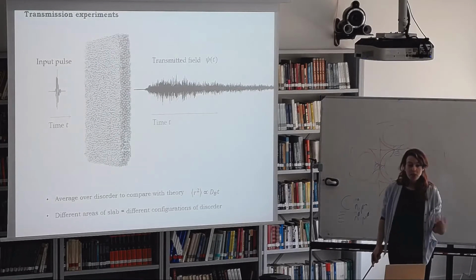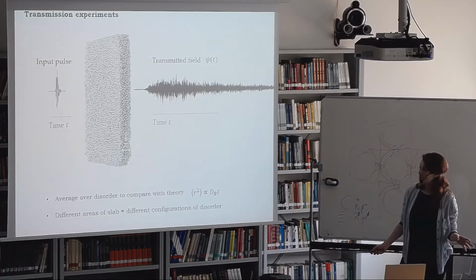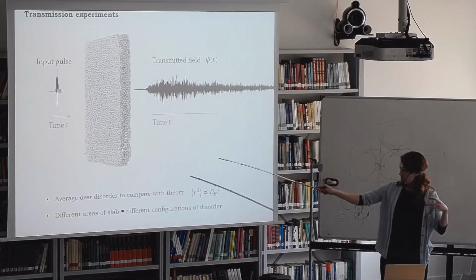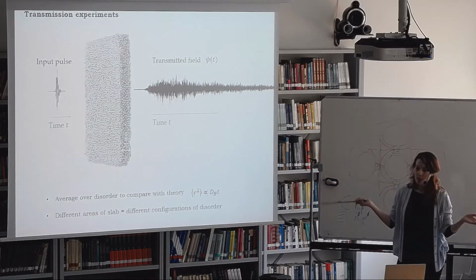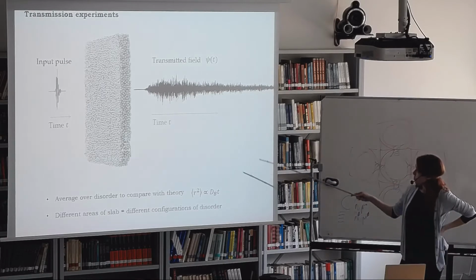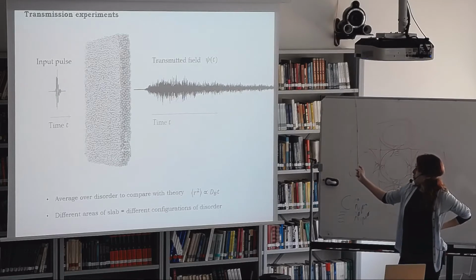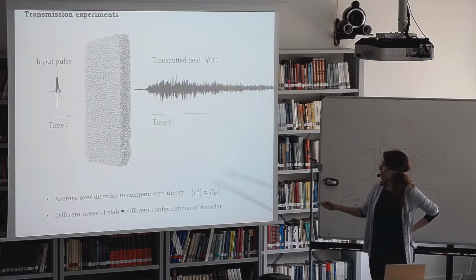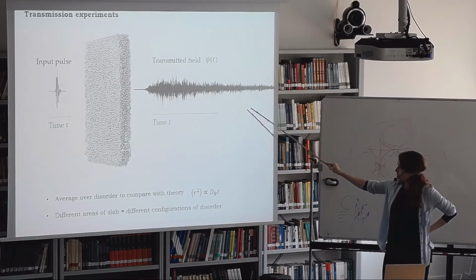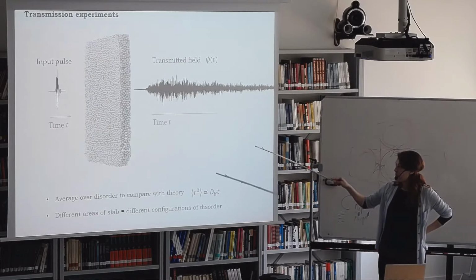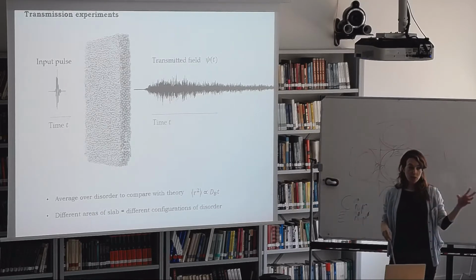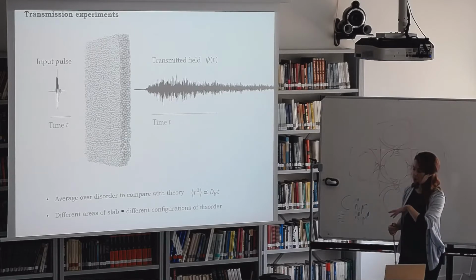OK, so all the experiments that we do on these samples basically involve sending in a short acoustic pulse and then looking at what comes out. So in transmission, what comes out is this field which extends super long in time. So all of these signals that are arriving at long times are waves that have been multiple scattered in the medium, so they spent a lot of time in the sample before escaping out the other side.